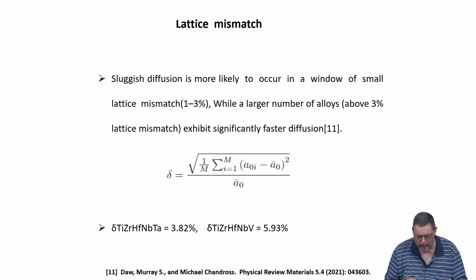And when we look at the lattice mismatch of these two alloys, they are both larger than 3%, so that might explain why here this high entropy approach has been overdone. So it's basically meaning you have added alloy constituents which do not really like to form a single phase solid solution. They still do, but they are on the brink of not doing. This is why they are also rather unstable against precipitate formation. And this means that here any type of entropic effect hindering diffusion is not present because it's overwhelmed by these potential energy fluctuations which give rise to accelerated diffusion in this very strong lattice mismatch condition.